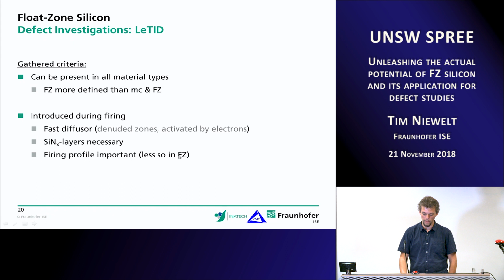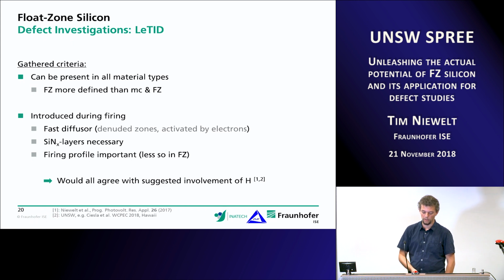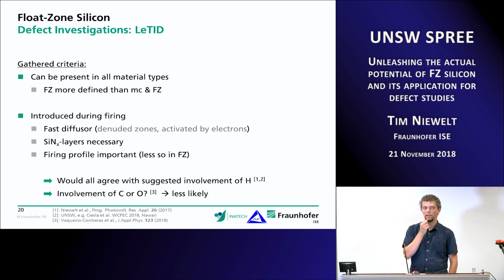And the firing profile is important, and the peak temperature is important, however not as important in float zone silicon. We think that all of these findings would agree quite well with the suggested involvement of hydrogen, as for example UNSW has been promoting a lot. We don't really see that carbon or oxygen would make sense with these findings, because there should be way less oxygen and also less carbon in float zone silicon. But despite that, we see quite strong degradation. So because we see the same amount of degradation, or sometimes even more degradation in float zone silicon, an involvement of carbon or oxygen is not that likely. But we're still searching for the actual defect.